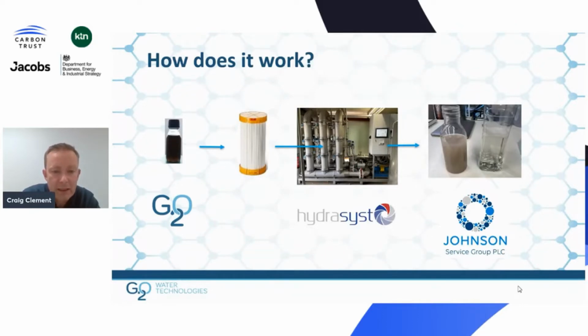The membrane is installed into the industrial laundry recycling system, as shown in the middle here. The system is provided by our partners Hydrasyst, and this system has 18 membranes. You can see here the 3 loops, and each loop contains 6 membranes. The industrial laundry recycling system is obviously cleaning the water. On the right hand side you can see a rather dirty waste stream that is cleaned with the use of the system.